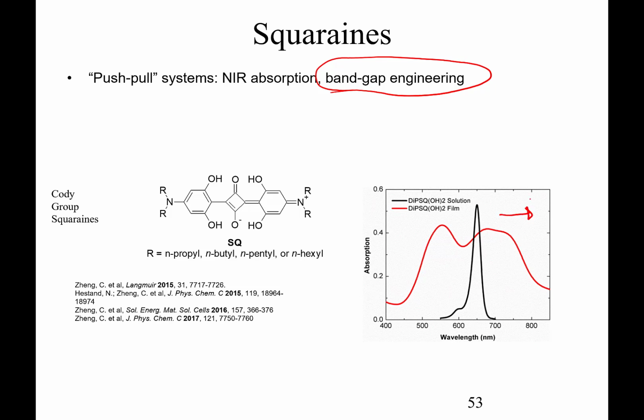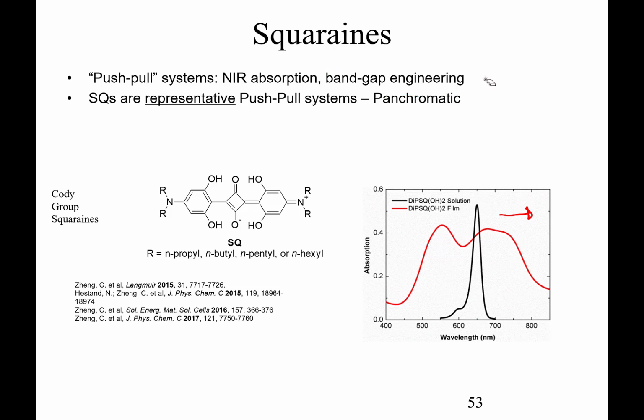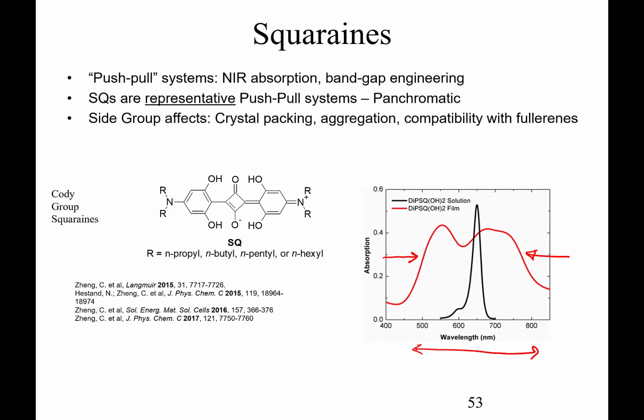So squaraines are very small molecules that are representative push-pull systems. And we're also saying that they are panchromatic. Panchromatic means they've got a very large full width half maximum here. So they absorb over 500 nanometers all the way out to 800 nanometers. The side group, as I've mentioned before, when we change the side groups in here, it affects the crystal packing, it affects the aggregation, and it also affects the compatibility and how well these materials mix with these fullerenes.